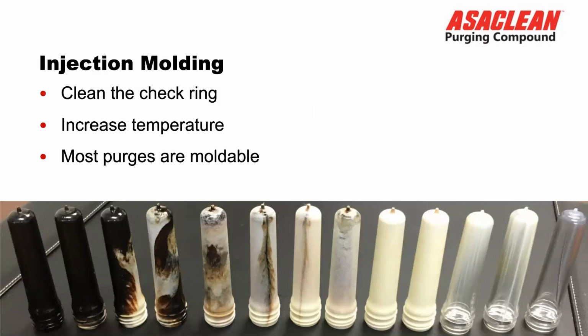Some tips in injection molding would be, for example, to improve the cleaning in the nozzle body area, the check ring area, which is really where the majority of hang-up can occur as far as the screw and barrel is concerned. Increasing the temperature in that nozzle body about 50 to 100 degrees can solve an issue that might otherwise be a nozzle body teardown that takes 4 hours. So be careful with resins that are likely to hang up in nozzle bodies, like Santoprene, for example, which is a real pain in the neck. But sometimes it's simply a nozzle body issue, or a nozzle body design issue.